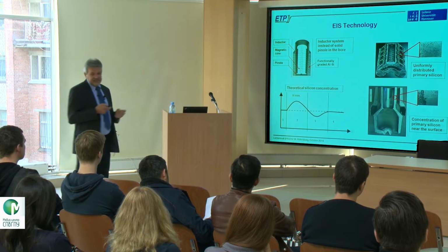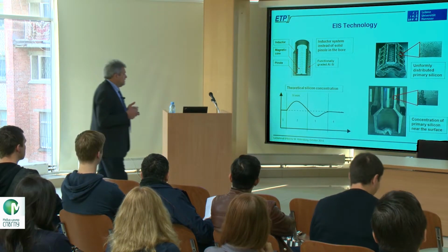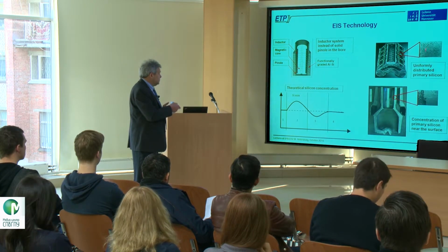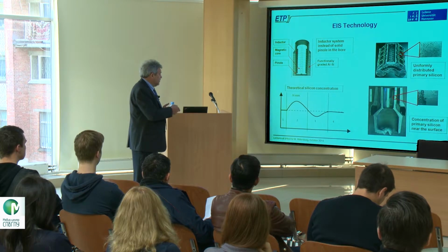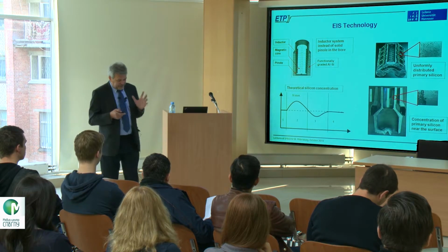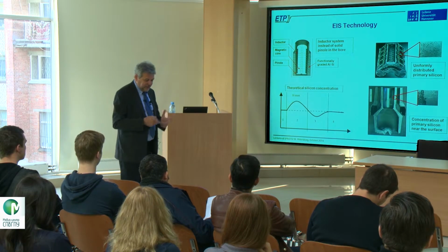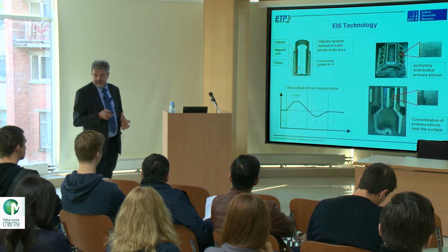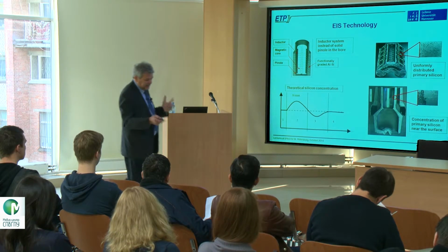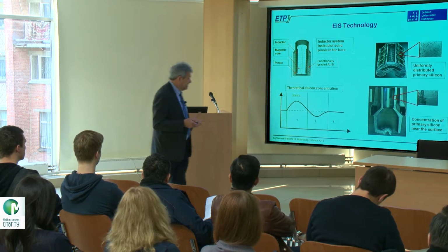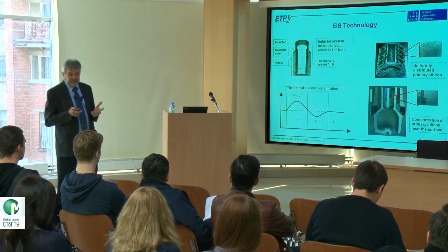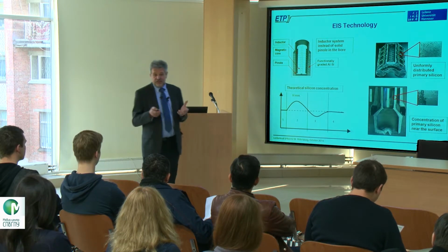So one very interesting idea came up: to concentrate these silicon particles only on the surface of these cylinders. Then of course you need, in general, on average, less silicon, because only here you need it. So in general you need not 18, 19%, maybe 15 or 14. And this is much more convenient. But how to concentrate them?